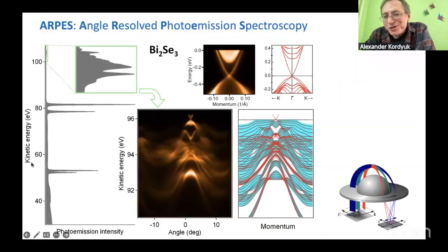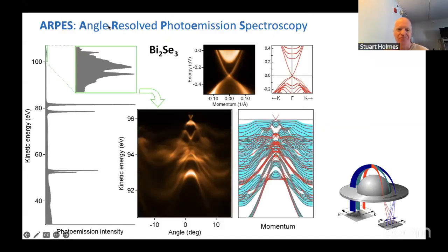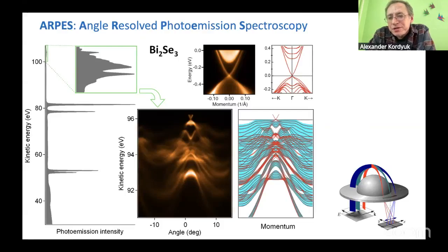Yeah, I just wanted to return to the slide. This is just our experimental data from when I measured my first impression about topological insulators, when they just started to appear, and ARPES spectra appeared. Here is just a bubble, that is nothing real. But then really we saw that there is such a surface state here. It is a surface state, okay. It's not something unusual, but surface states in normal crystals are very sensitive to the cleanness of the surface. Any dirt on the surface just kills the surface state.